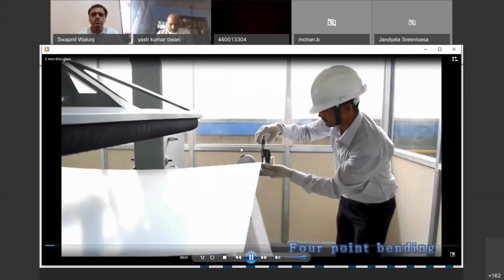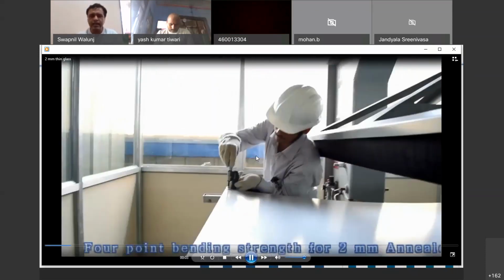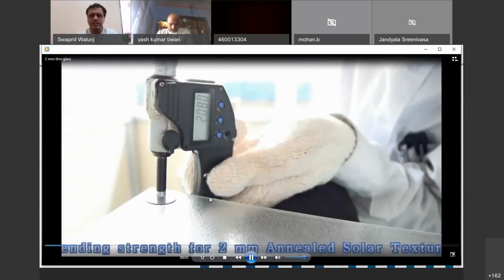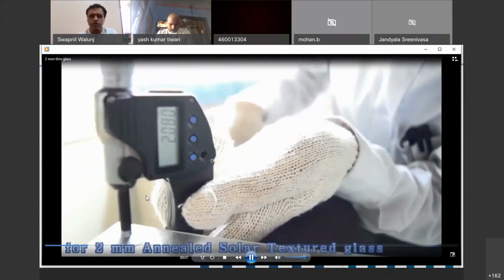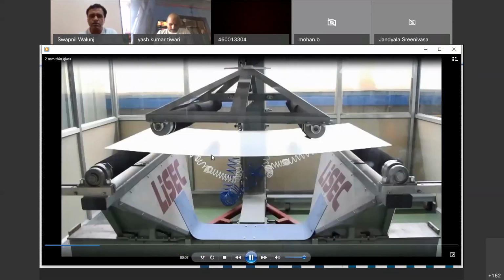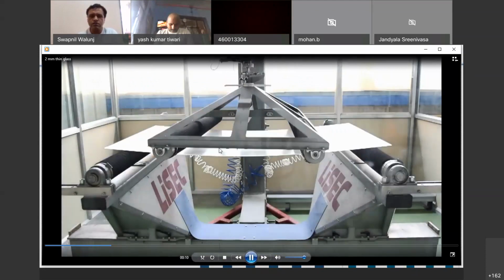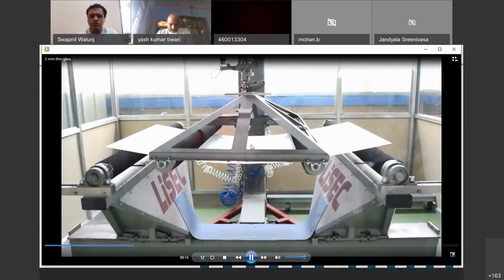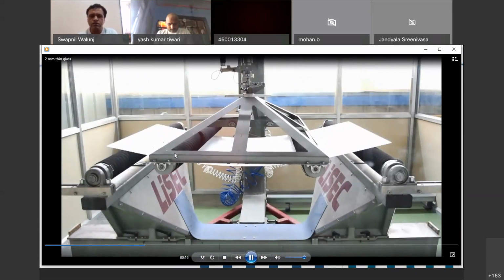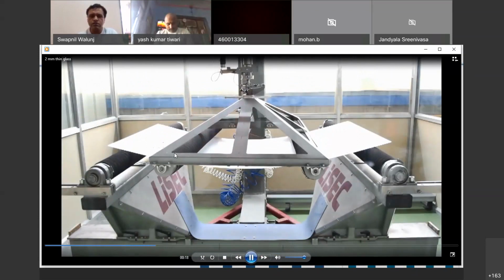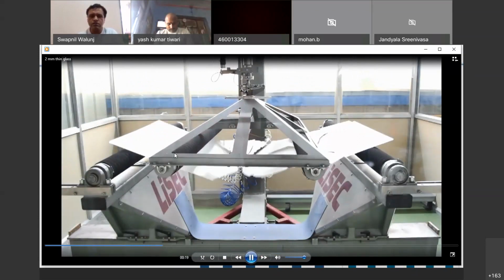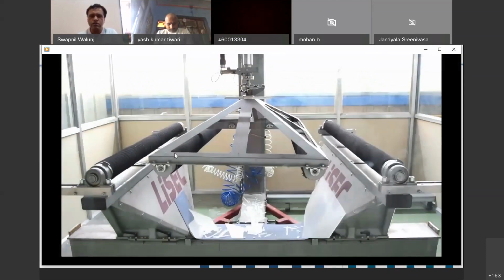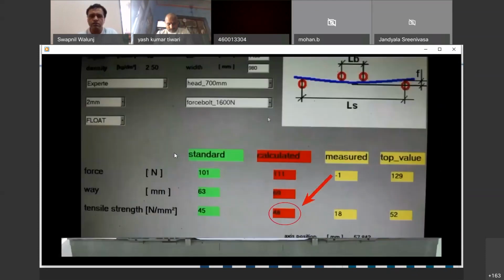This is called a 4-point bending test. This is 2 mm thick glass. This is an annealed glass that we have. We are putting it on a 4-point bending machine where the force is now getting applied and the glass is getting bent. So this is the annealed glass that you are seeing. It has broken, and if I have to show you the number, it's around 18 Newton per mm square.